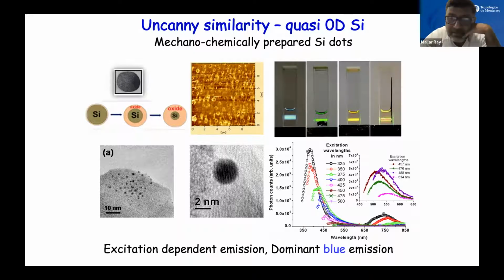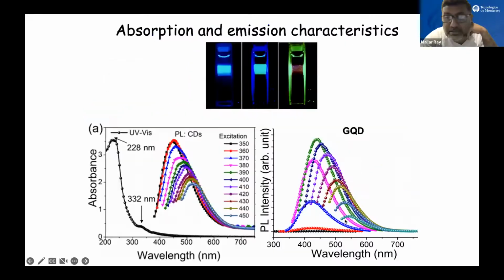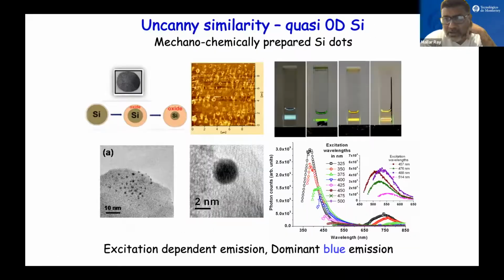And interestingly, the emission pattern of the silicon quantum dots is very similar to the emission patterns that we obtain in carbon. Now, why is it so? Some of you might know, if you're working with silicon and carbon, there has been research on photoluminescence from silicon for the last 30 years. Many groups in the world worked on it. Many groups in the world are working on carbon dots, graphene quantum dots. But till now, we do not have a conclusive understanding of the emission mechanism that is operative in carbon and silicon systems. So this kind of uncanny similarity between silicon and carbon dots, in my opinion, gives us more food for thought to think what exactly might be happening.